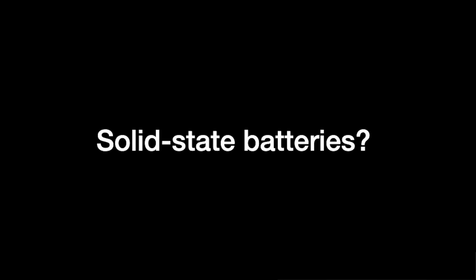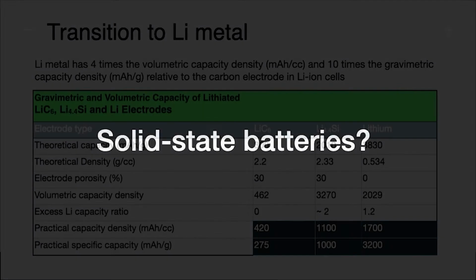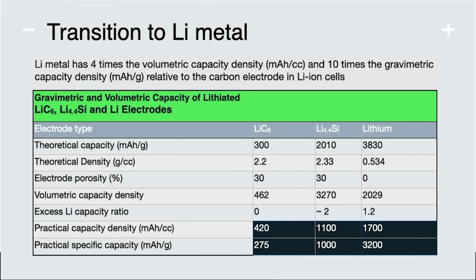Polyplus is certainly working in this domain as well. So what about solid state batteries? It's likely and almost certain that as we move to solid state, that will also involve a transition to metallic lithium for the negative electrode. And the reasons for that are obvious. Lithium has 4 times the volumetric capacity density of carbon, and more than 10 times the gravimetric capacity density of carbon. So there's a big jump in performance if we can do this. And in fact, if this is successful, then that's kind of the end of the development of a negative electrode, right? Because lithium is as good as you can get.